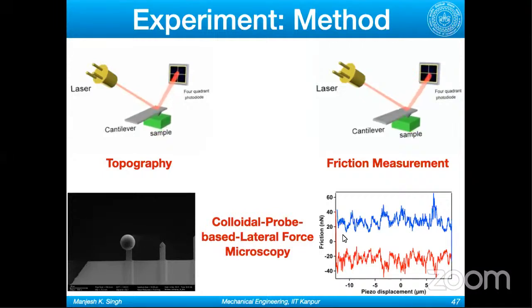In AFM, normally you have a trace and a retrace curve, and then you take the average of these two curves, and from there you get the friction force. So this is the trace curve, this is the retrace curve. You do this minus this divided by 2. If you want to take an average, you can take the modulus value of each of these, or you can just simply subtract one from the other and divide it by 2. You will have the friction force. You have applied the normal force or voltage. You know the sensitivity and the stiffness, so you know the normal force, you know the friction force, so you can get the coefficient of friction.